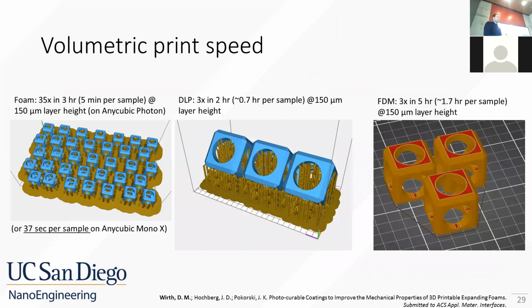How does this relate to volumetric prints? Well, if we look at how long it takes to print a 1-inch sample cube using FDM, it takes about 1.7 hours per cube. Using a DLP or mass SLA process, we can cut this down to 0.7 hours per sample. Now, this is all at 150 micron layer height.